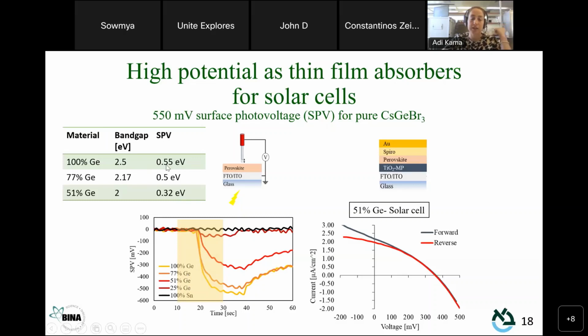change. It's Fermi level splitting change, which is considerably very good for very new materials that haven't been explored before. And it indicates a very good potential. If we can get a complete coverage, we can actually make quite a good solar cell with those materials.